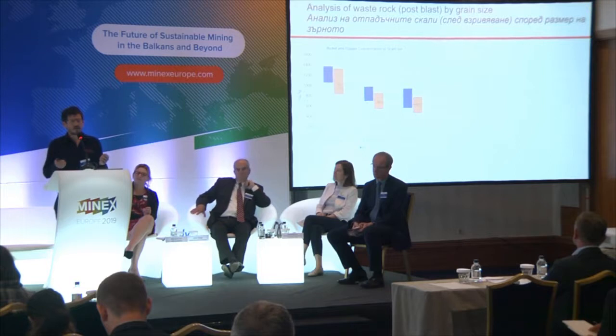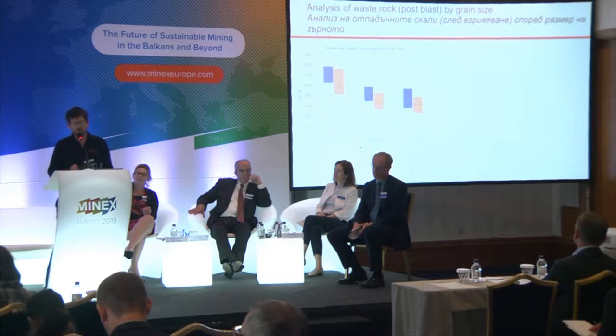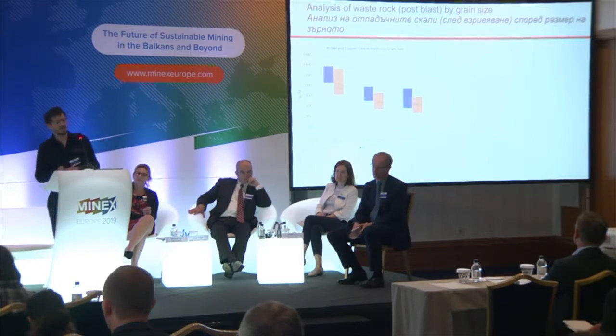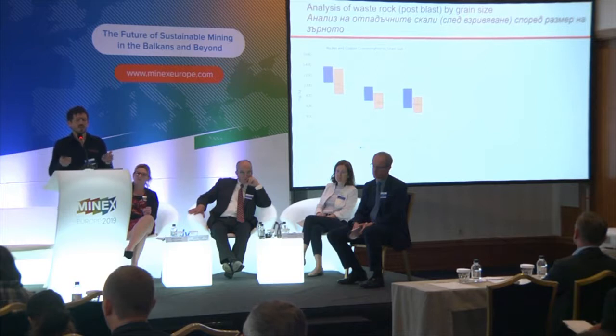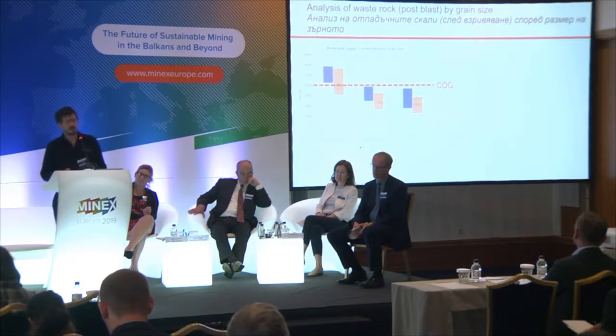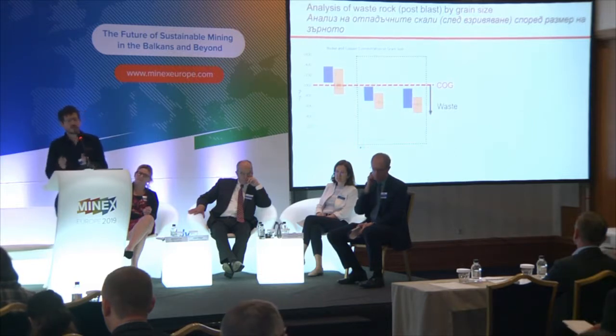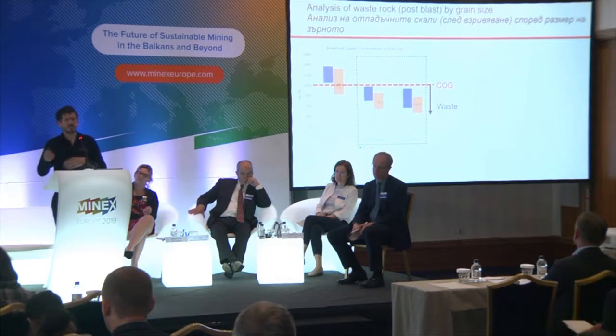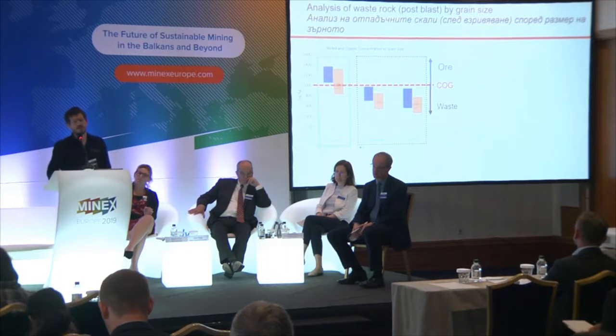Then, if we want to look at the opportunity aspect of this, data is showing particle size on the x-axis, and on the y-axis is grade of nickel and copper. And it's a distribution plot because it's on a lot of samples. And you can clearly see that if we put a cut-off grade arbitrarily in here at 1,000 ppm, the coarser material is waste. So our block model said it's waste, and it is waste. However, the fine material is actually above the cut-off grade, it's actually ore. So this is waste material, contains some ore-grade material.